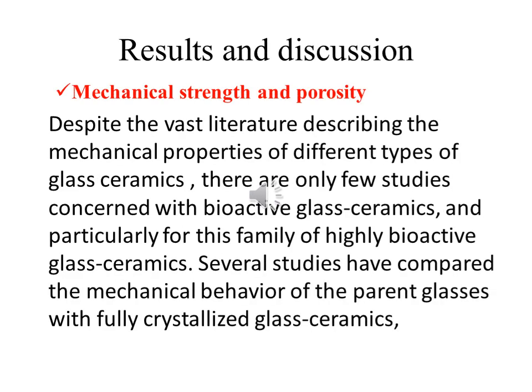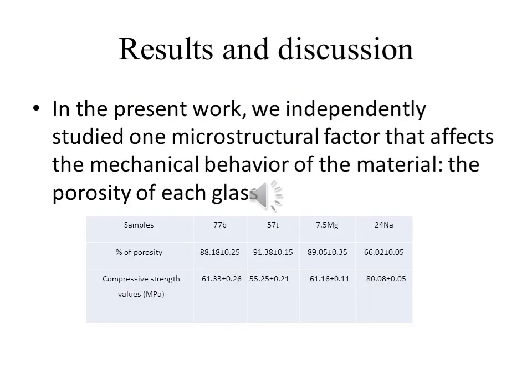For the results of mechanical strength and porosity, we can say, despite the vast literature describing the mechanical properties of different types of glass ceramics, there are only few studies concerned with bioactive glass ceramics, and particularly for this family of highly bioactive glass ceramics. Several studies have compared the mechanical behavior of the parent glasses with fully crystallized glass ceramics. We present the result in this table. In the present work, we independently studied one microstructural factor that affects the mechanical behavior of the material, the porosity of each glass.